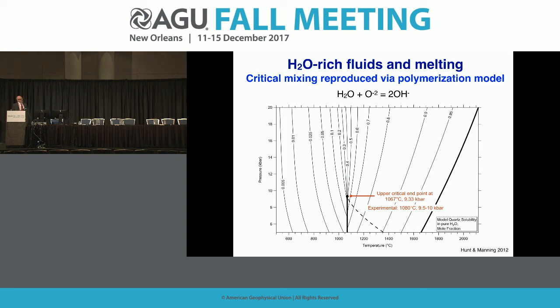We predict the location of the upper critical endpoint at 1067 degrees C and 9.3 kilobars. And when you compare that to what's actually been observed experimentally, it's remarkably good: 1080 degrees C and 9.5 to 10 kilobars from experiments of Kennedy and others. And we've reproduced that to just confirm it. A polymerization model, therefore, is successful at predicting solubility isopleths, which are shown in the light lines here, melting location, and the presence or absence of critical mixing, simply based on a very simple model like this.